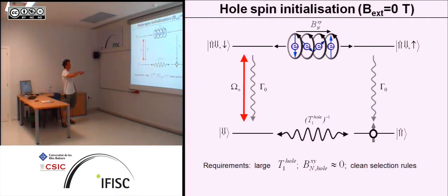So we use this scheme now to, for example, excite with the sigma plus laser. You couple these two levels. If we go just in terms of populations, we populate the excited state. The electron spin now, because of the strong contact interaction and because it doesn't have any orientational asymmetry, couples to the nuclear spin and starts to precess in the vertical component of the nuclear magnetic field. Thereby you have a coupling mechanism between electron spin down and electron spin up. Now, due to spontaneous relaxation, you can either relax into that state, where you are just excited again, or you relax into here. And then you're trapped here, for the case that you have long relaxation times and that the hole spin doesn't precess in the nuclear field itself. So that's our idea of the system.